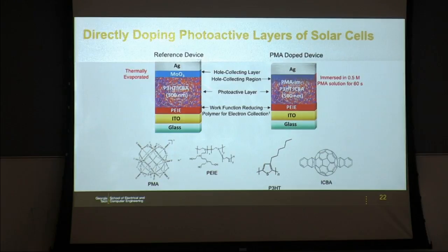But instead of fabricating that separate film here of molybdenum oxide, which requires vacuum deposition, and also molybdenum oxide is quite air sensitive, so you have to package these devices, which is a challenge, you can also take the blend of these two materials and apply the same doping technique. So you spin coat the blend of these materials, you have your thin film, and then all you have to do is just dip it in a solution of PMA for about a few minutes at room temperature, and you get that doping over a typical thickness of 10 to 20 nanometers.